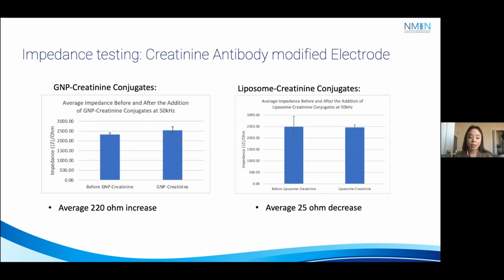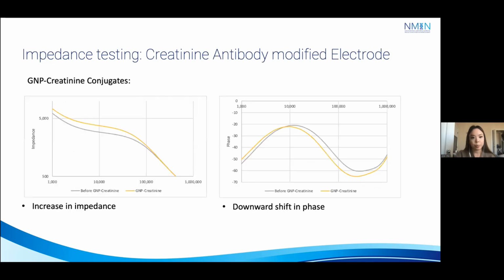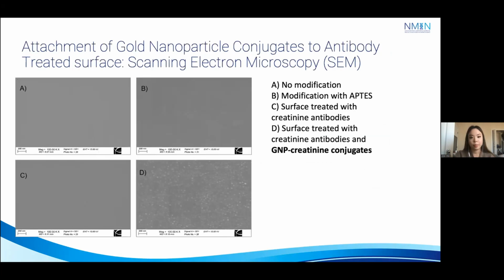So perhaps suggesting a more sensitive system using the gold nanoparticle conjugates compared to the liposome creatinine conjugates, which is, again, a similar trend where we see a more sensitive system with the gold nanoparticle conjugates in the acetylspermine test as well. And again, we were able to see this in a single electrode treated with the gold nanoparticle creatinine conjugates, a characteristic increase in impedance and downward shift in phase.